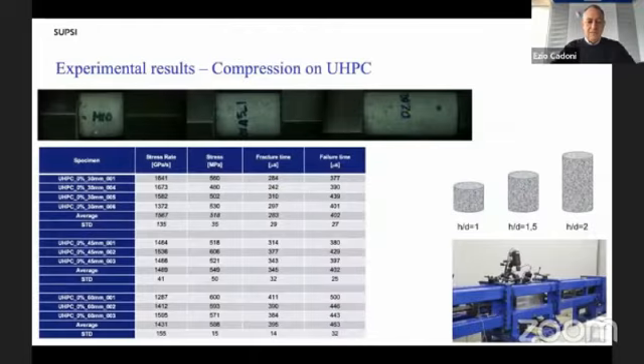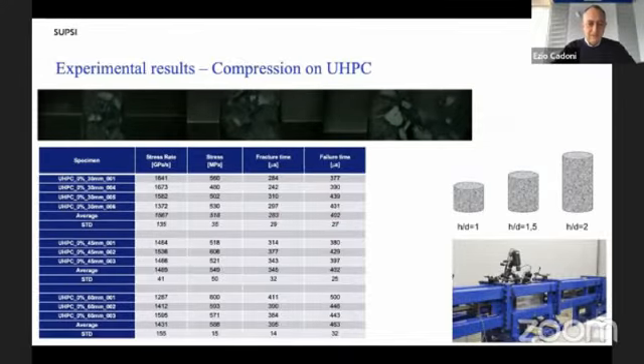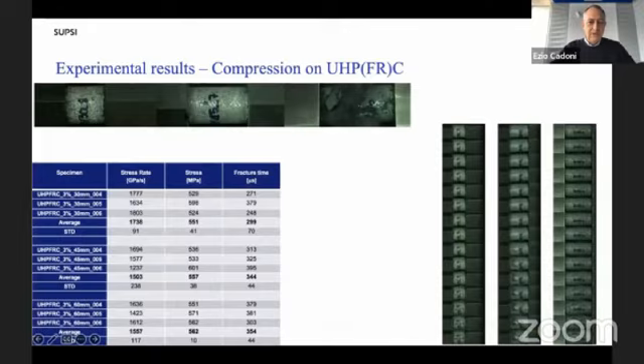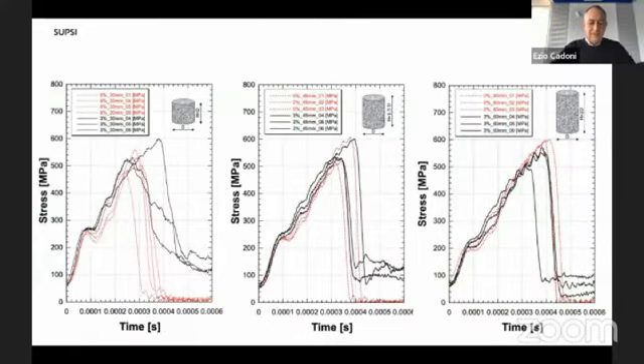In the next two slides, I'm presenting the results of the two materials with the same preloading conditions. This is the result for the matrix, the UHPC, in which this is the evolution of cracks. This is an example of fiber reinforced material. In this slide, I've shown the comparison between the two materials, matrix and fiber reinforced one, in terms of experimental stress time curves. The peak load seems not to be influenced by the presence of the fiber, while the post-peak is governed by the fiber content, and this influence decreases with increasing the specimen length.